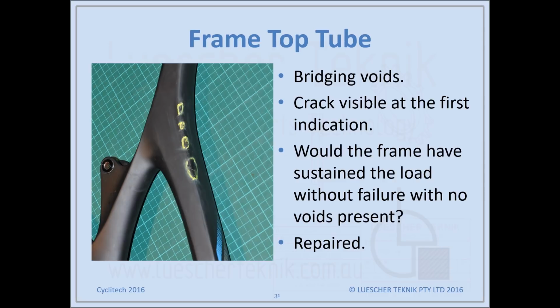Another common thing is bridging voids. Where you have a corner on the tube, the sharper the corner is, the more likely you are to get bridging voids. Bridging voids are where, when the fiber's being laid into the tool, into the mold, you're not getting it right into the corner. So when it's cured, you have this void along the corner of that section.